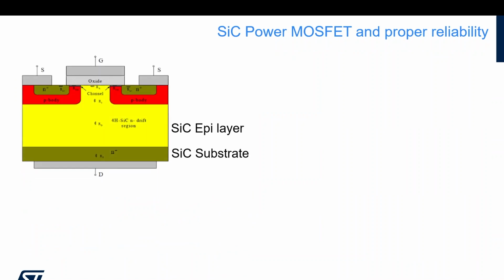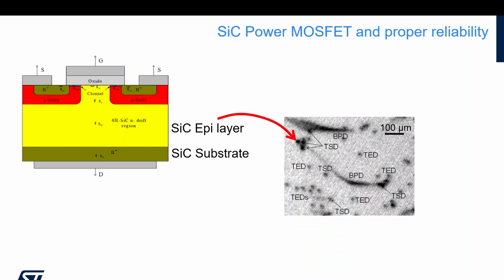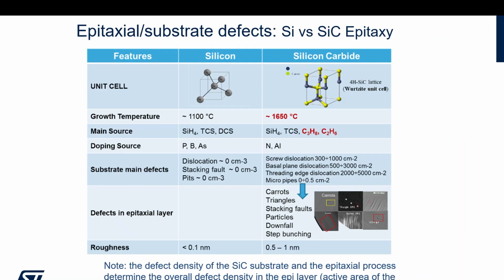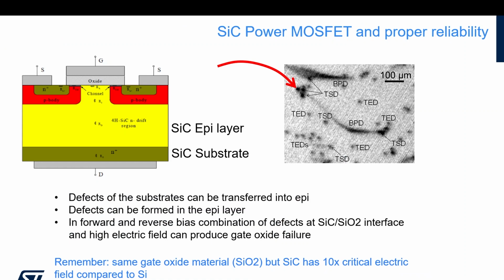Of course, as I said to you, you always have to pay. Nothing is for free in life. And the point is that if this is not silicon anymore, but silicon carbide, then the substrate is not free of defects, the epitaxy is not free of defects, and also the surface of your device, if you etch, shows you defects. So you have to be careful, because these defects can be mitigated through the proper EPI process.